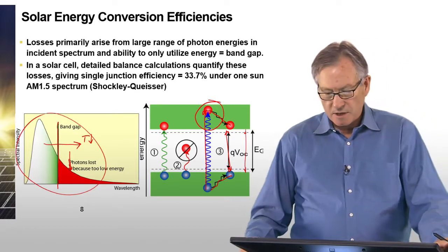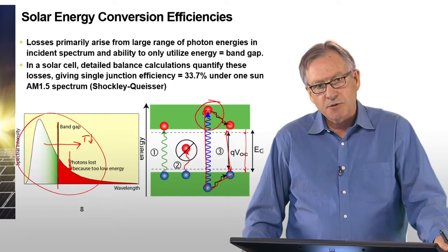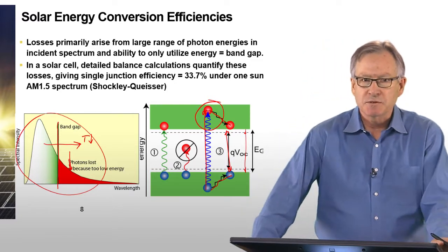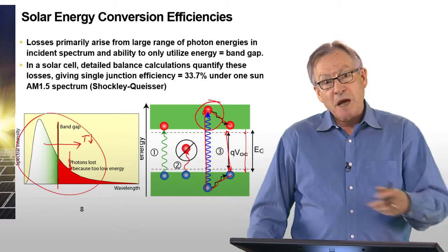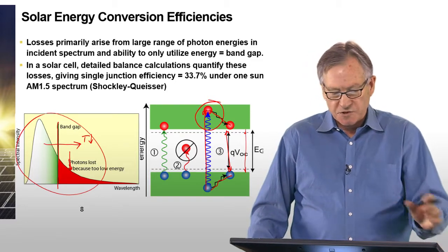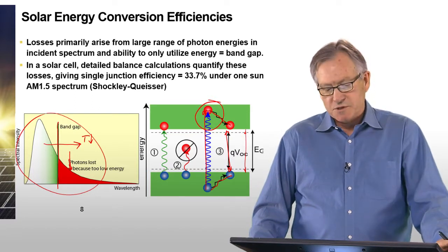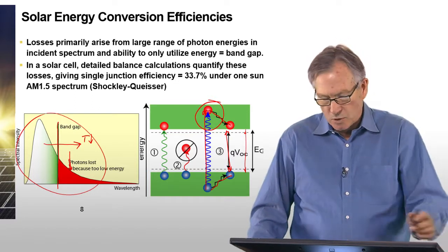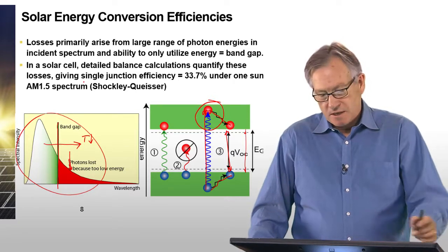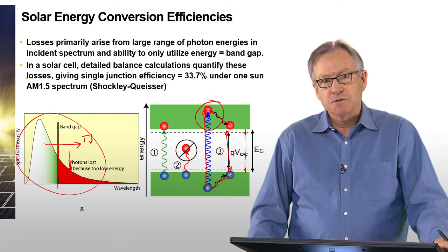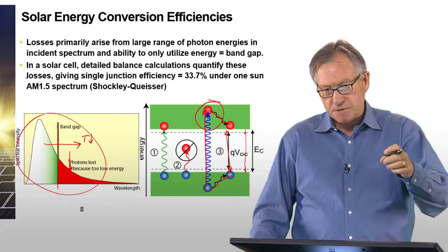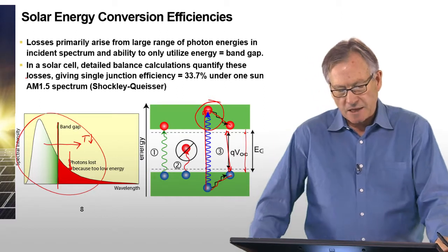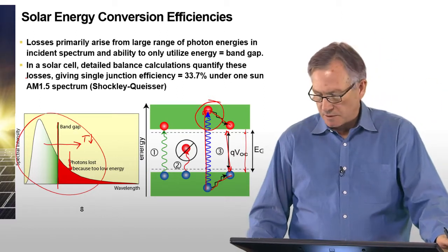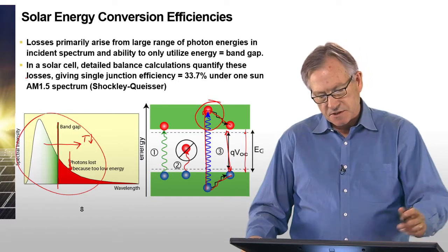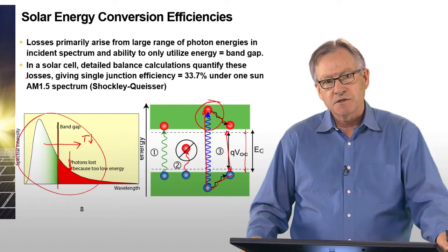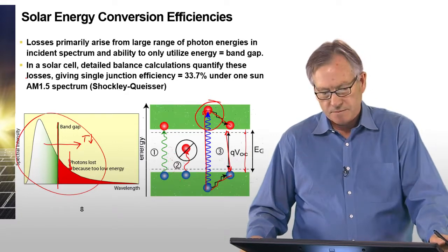Because of this, an analysis was done using a process called detailed balance, which is an ideal thermodynamic analysis of the maximum efficiency of a solar cell with a single band gap under what's called one sun intensity. In particular, AM 1.5 refers to the spectrum of light that's seen at the Earth's surface at a certain latitude. That latitude is approximately the latitude of Denver in this case. In any case, this analysis showed that the maximum efficiency for a single gap is 33.7%.